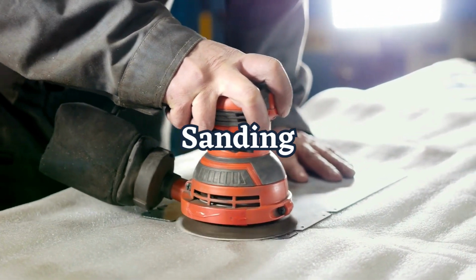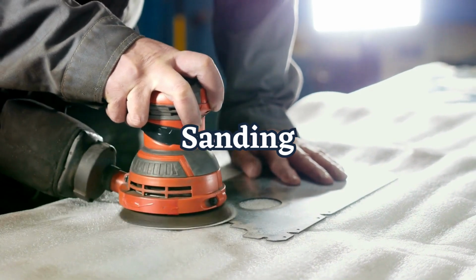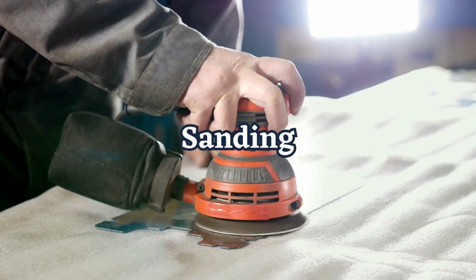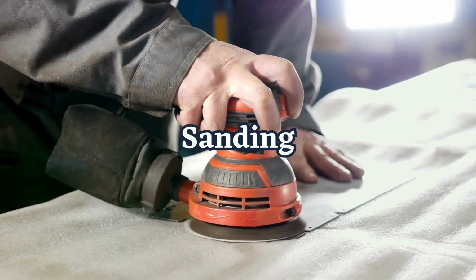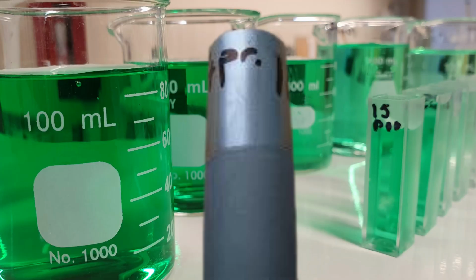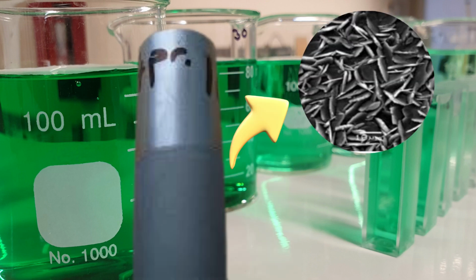Mechanical cleaning such as sanding with the different grades of emery sheets and polishing increases the active sites on the bare metal. The electrochemical reaction is the initial corrosion step occurring on the bare metal. The acidic nature of phosphate coating increases more active sites that enhance the kinetics of nucleation of phosphate crystals, that is, quick phosphating and coating with smaller grains.